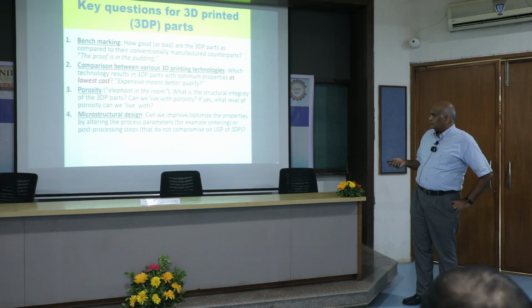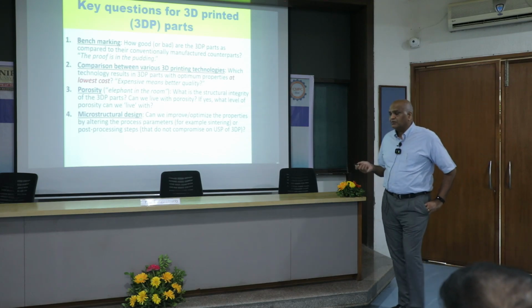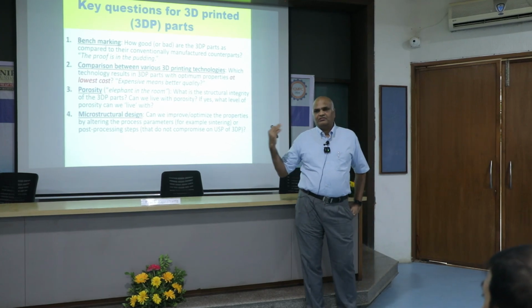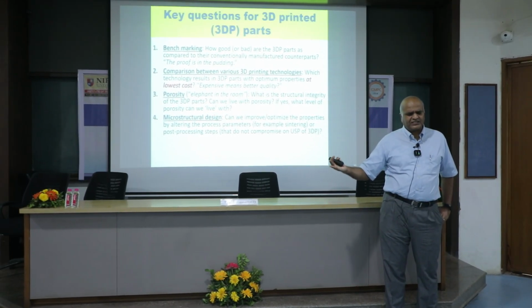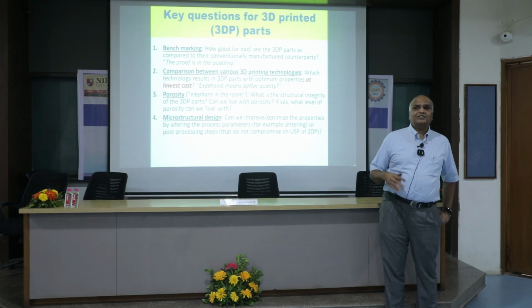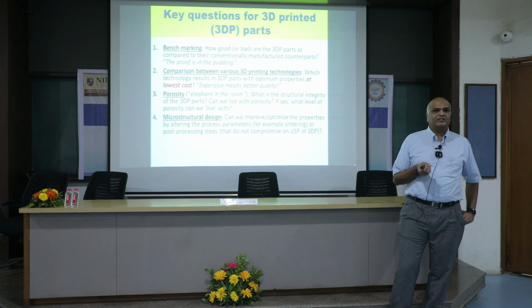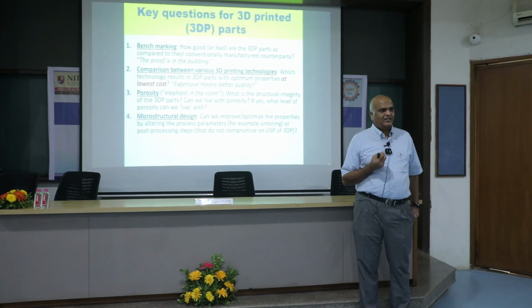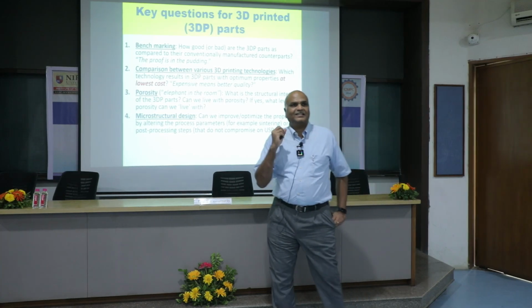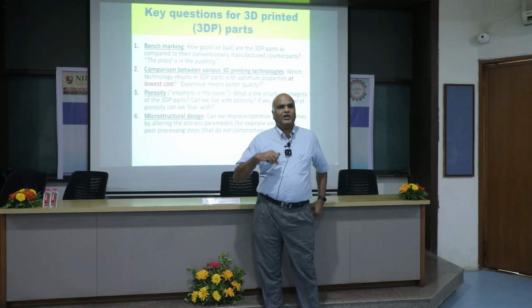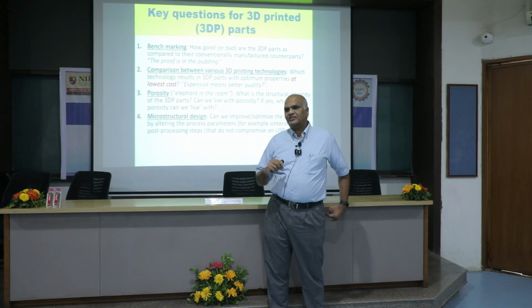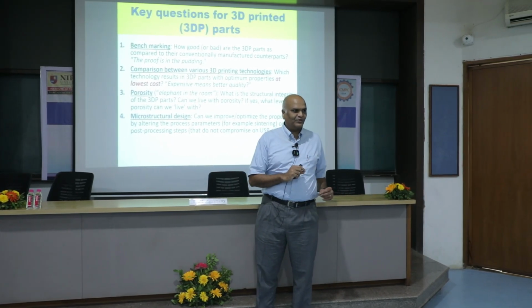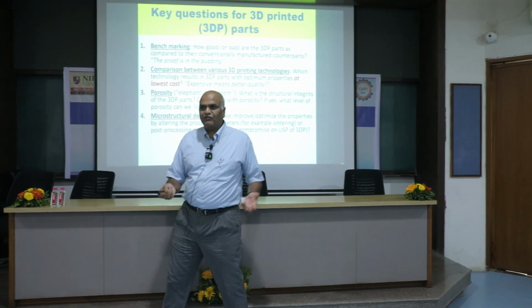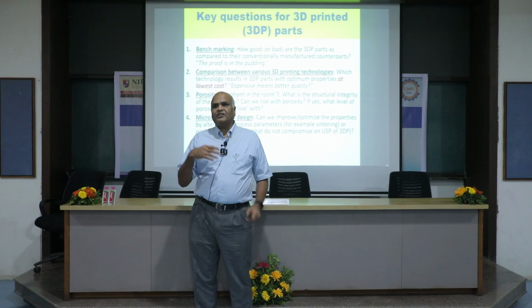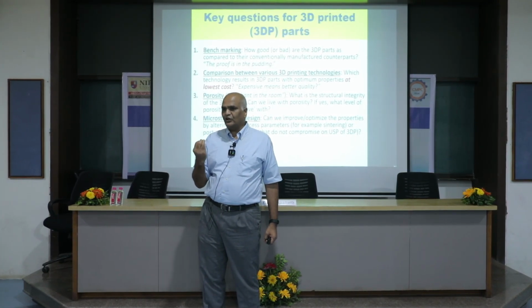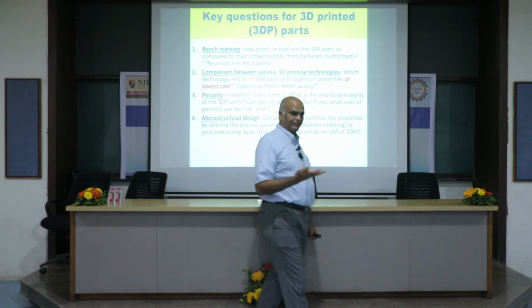Okay. So the final thing is porosity. Now, this is not applied to wire arc additive manufacturing, but to the powder-based one. So powder metallurgy, we know that anytime you use powders, you always will have porosity, right? Pores, right? These pores are deadly from a fatigue perspective. Okay, so if you are going to use a one-off, if it is a rocket that's only used once, it's okay, no problem. But if you are going to use it again and again in a washing machine part, a car part, etc., right? Then the pores will act as crack initiators under fatigue loading. Okay, and then the life of the component will be very low.